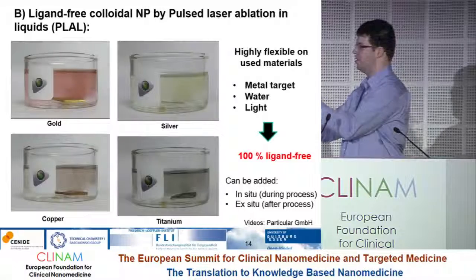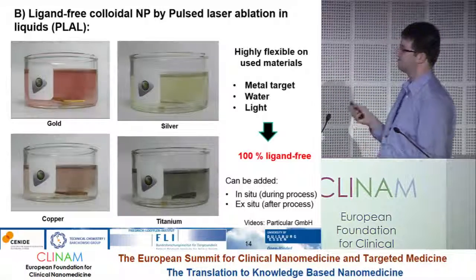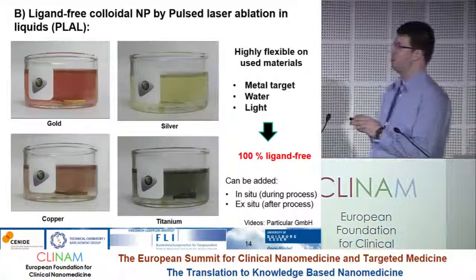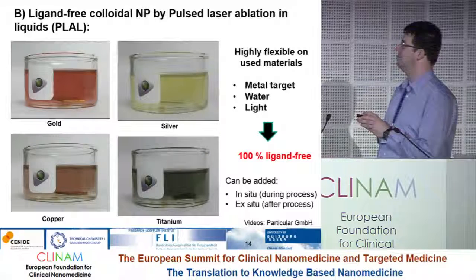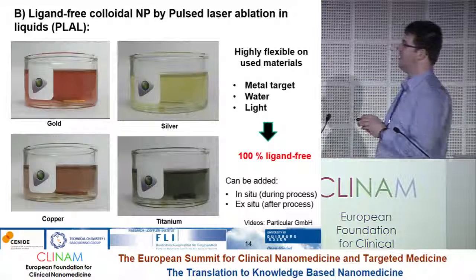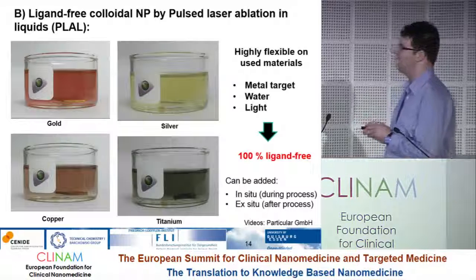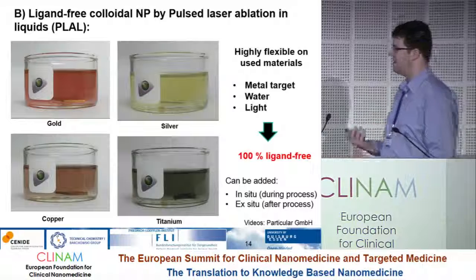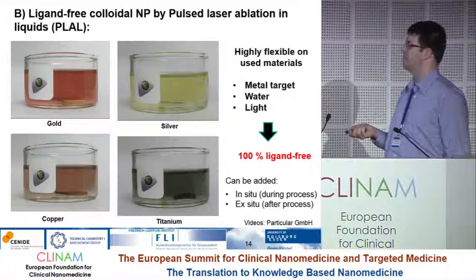We just put a piece of metal into a beaker, focus a laser beam on the target, move it with a scanner, and then we can fabricate our nanoparticles. We only have the metal target, water, and we need light, so we have 100% ligand-free nanoparticles, while the ligands can be added afterwards. So we have a very good model system.